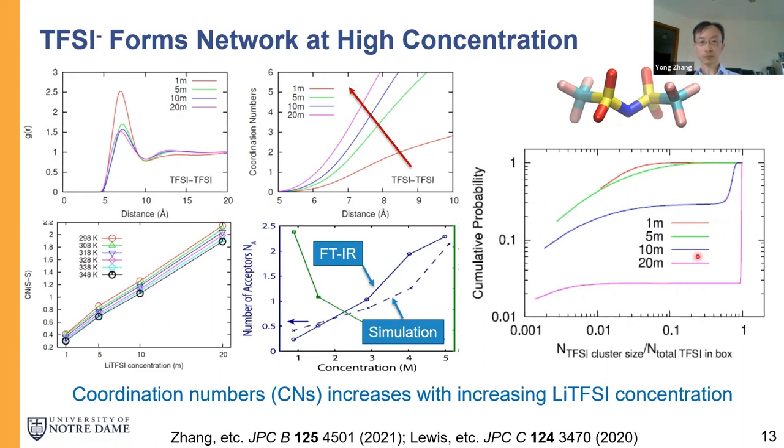Then at 20 molal, there's only a small number, like 2 or 3% of LiTFSI, that are in a small cluster form. All the others, basically the whole liquid, is a big network of LiTFSI. So this is really interesting, this conversion from isolated LiTFSI to a big network.